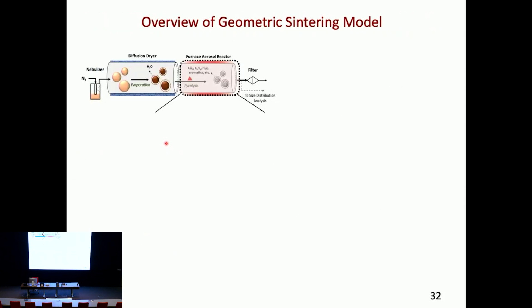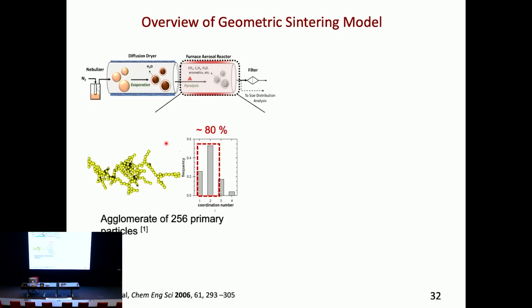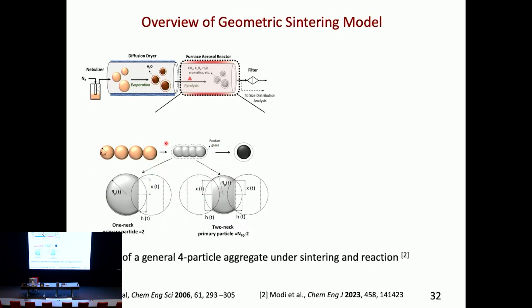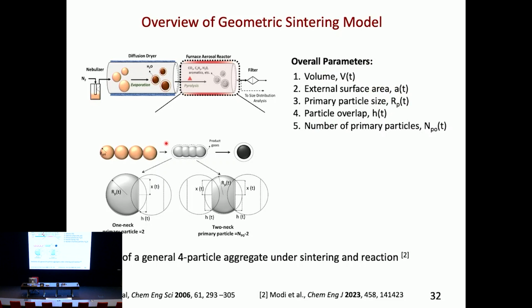So I go back to my laboratory scale system. And before that, I need a sintering model. It's not readily available for some of these species. So you see that I can form these agglomerate structures with a lot of neighboring particles, but most of them have a single neighbor or a second neighbor, right? So I'm going to forget the larger coordination number clusters, and that's of course an assumption. Then I bring in the concept of certain geometrical models, and when I have two, you can see that there are certain parameters, and again, I'm not going into great detail here, but I basically want to get expressions for each of those parameters as a function of time, and of course, simultaneously with reaction taking place.